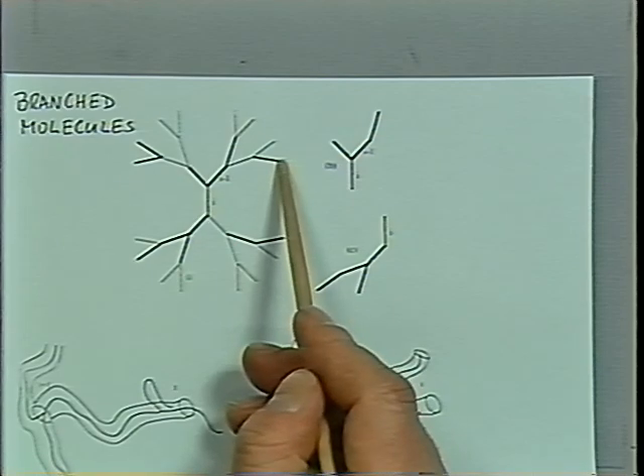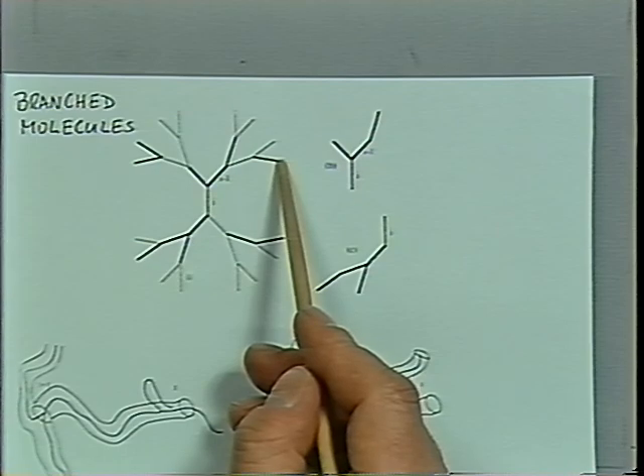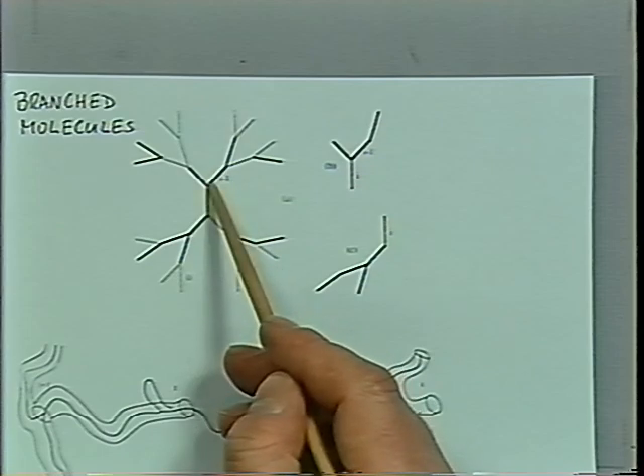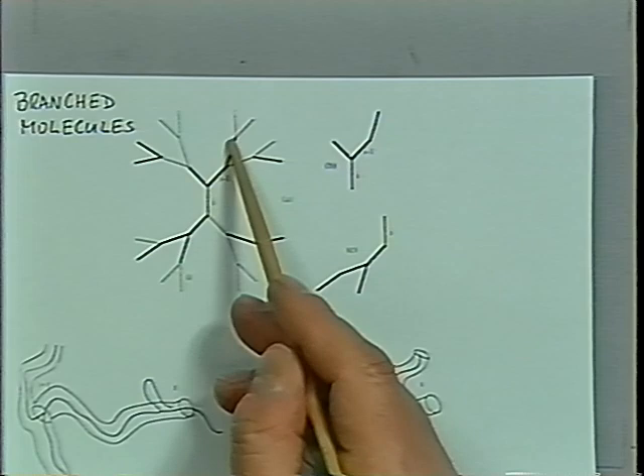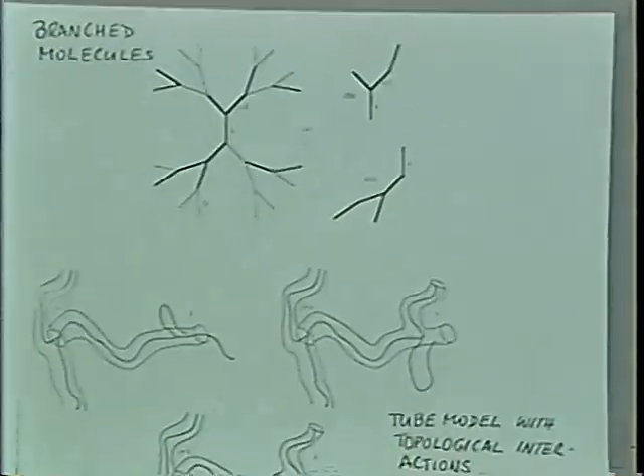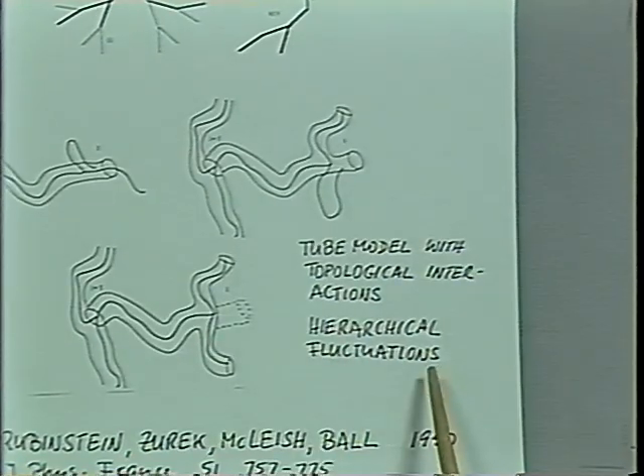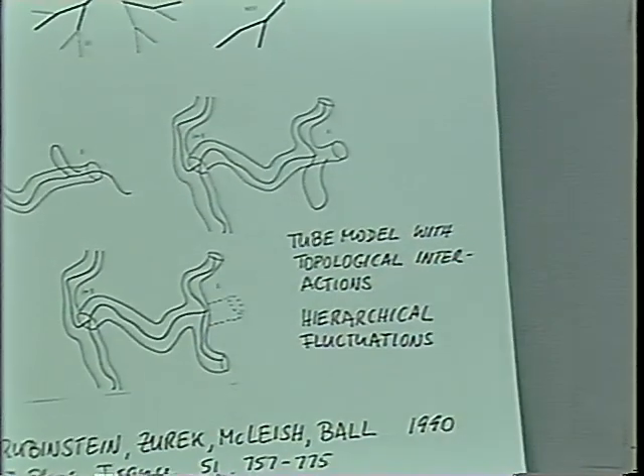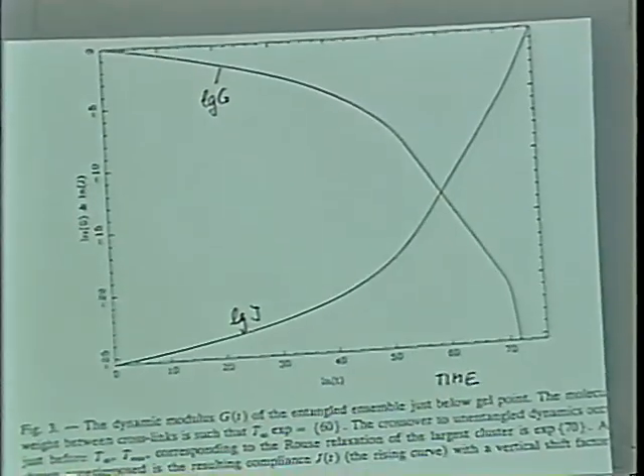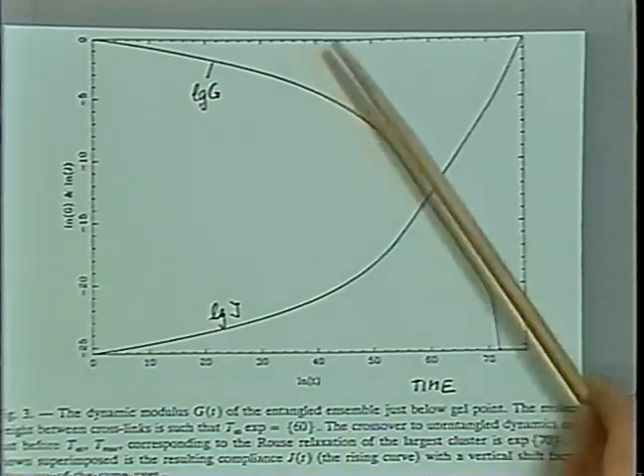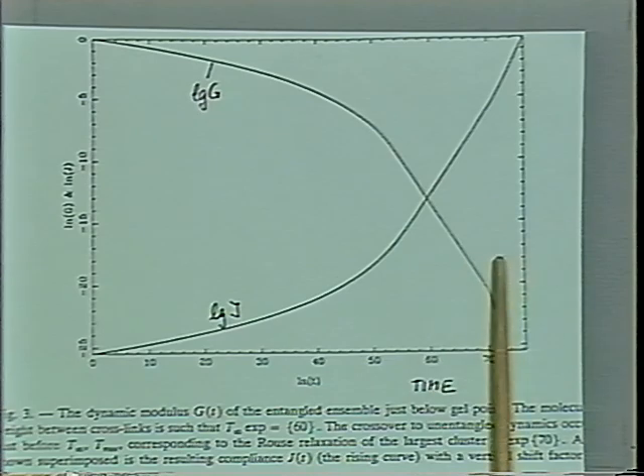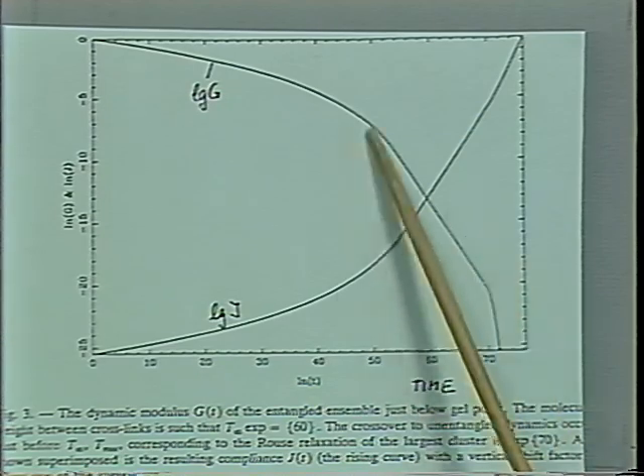And these authors now claim you should use a hierarchy of relaxation phenomena. This would relax first, this would relax next, and then this would relax next. And this only can relax if those two are relaxed, and those two relaxed need this other relaxing. So they have a special type of hierarchical fluctuations model which describes the behavior in an interesting fashion. And they indeed calculate a relaxation modulus. See, they don't calculate a spectrum, they calculate the relaxation modulus, and they find a power law behavior. Here you could describe this spectrum with a power law region, and then this is cut off when you hit the end of the molecule. The finite size of the molecule gives you a longest relaxation time. And then there's a distribution of short ones.